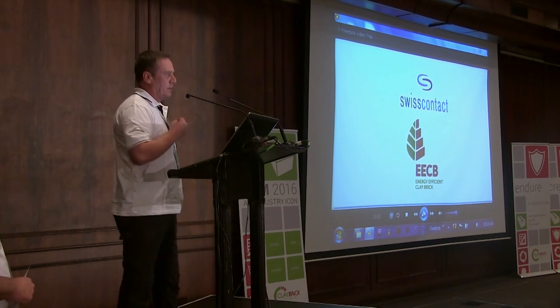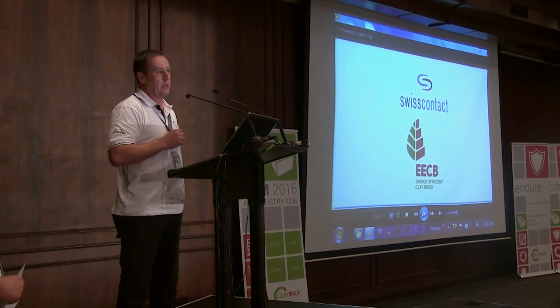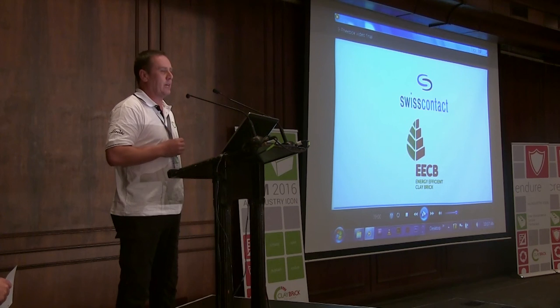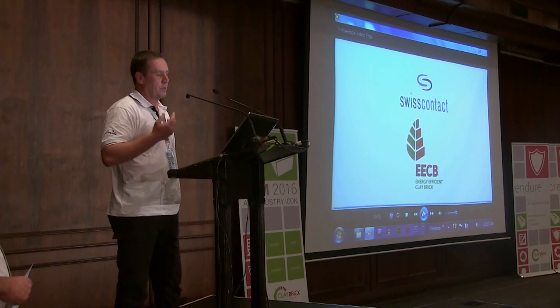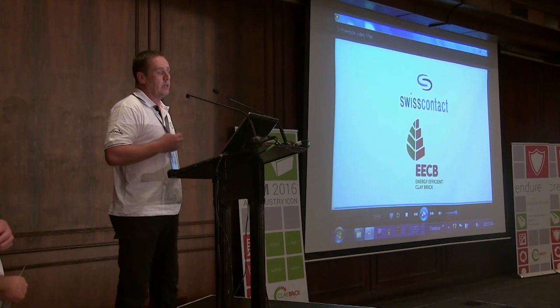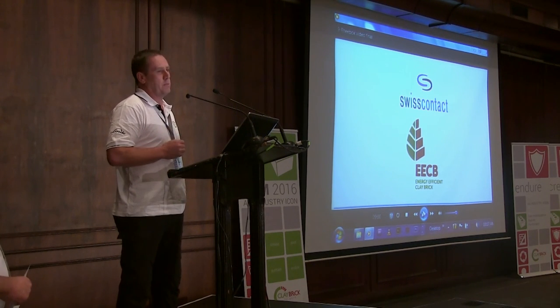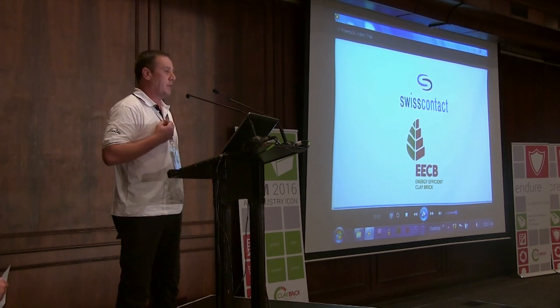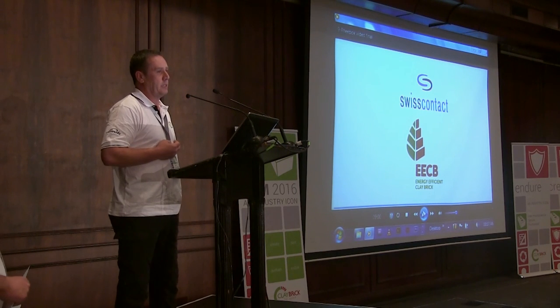Something important not in the video is that these are air-dried bricks. Nicky told me he had them down to about 3–4% moisture — but some were closer to 10%, and the typical average is around 6–7% moisture content. People said to me you can't fire above 2% moisture. Well, we are, and we're doing it successfully.